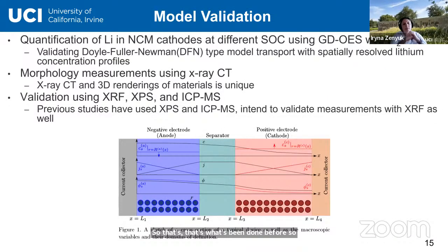So what is one trying to answer using this? What type of questions would one like to answer? In terms of modeling efforts, a lot of groups still use the Doyle-Fuller-Newman model, right? That type of model can predict the concentration of lithium in the anode and cathode versus various drive cycles or cycling profiles. That's one of the motivations to validate the model, because we can really use GDOES to tell us how much lithium is at any stage or during the cycling, right? Another possibility is to use glow discharge optical emission spectroscopy to probe the solid electrolyte interface.